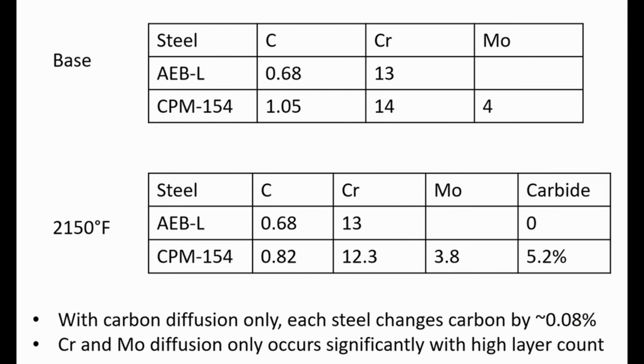One more example of times when carbon does not fully equalize. So I talked about AEB-L 154CM Damascus earlier. So the AEB-L has 68 points of carbon and 154CM has 1.05% carbon. So you'd think those would fully equalize and end up with the same carbon content. But remember also that there are carbides that stick around at high temperature in the 154CM. And so those carbides aren't going anywhere.